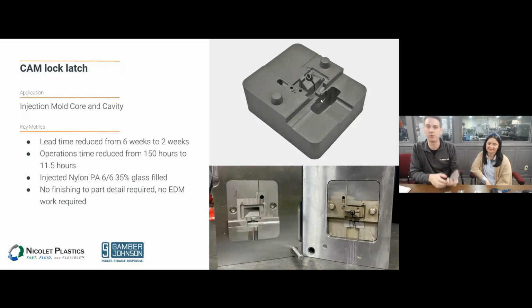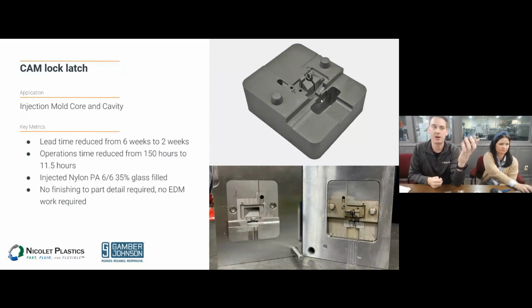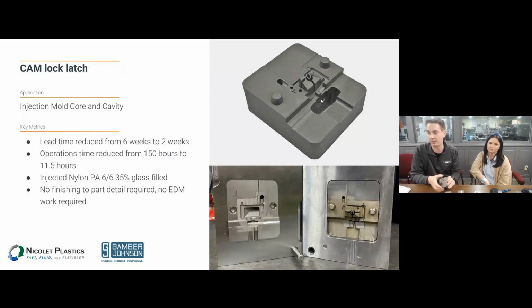The actual part was relatively complex, as you can see from all these different angled faces, so again, it would have required extensive EDM work to produce. In addition, the plastic part was being produced in nylon 6/6 that was 35% glass filled, a relatively abrasive material that required a tool steel insert. Using Mantle's technology, they went from a 6-week lead time down to just 2 weeks. In terms of operation time, it went from 150 hours of operations down to 11 and a half hours. All they had to do after printing was dust up the parting line, grind the outside, and add the ejector pin locations so they could get it into the mold frame.